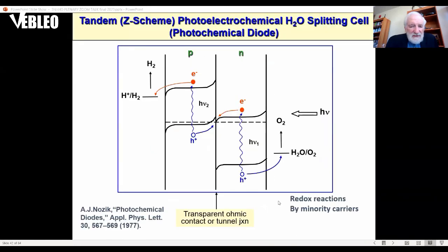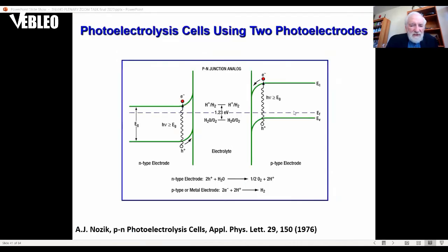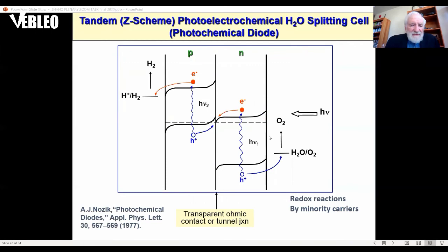Now, just moving quickly, getting to the end, for solar fuels, it turns out the analysis shows you need 2 semiconductors connected either in the photochemical diode, like in this array, which is just two electrodes with 2 different band gaps. And if they're simultaneously splitting water, because the total voltage is greater than 1.23 plus the overpotential, which is about 0.6, you can split water without having an external current, a wire, and it can just have a monolithic structure with 2 band gaps combined in this fashion.